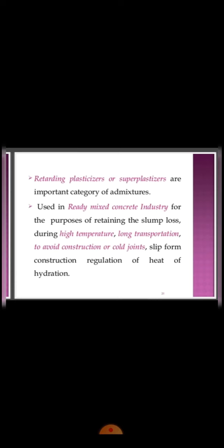As with plasticizers, ultimate strength gain increases as water is reduced. Set retardation allows the slower formation of a more ordered, smaller, denser cementitious matrix. This increases ultimate strength relative to an unretarded mix with the same water cement ratio. Provided that the concrete is properly cured, retarded concrete should be stronger and just as durable as equivalent plain concrete.